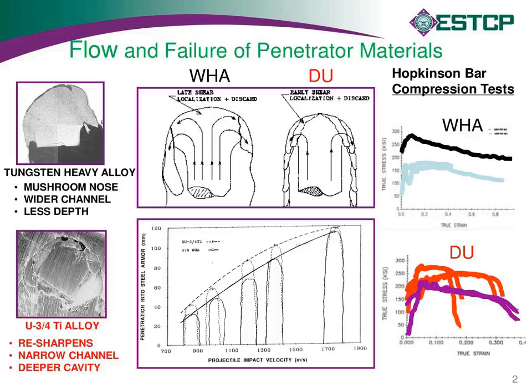The other thing I'll point out on this chart is an instrumented mechanical test where you can see this behavior kicking in. If you do a dynamic compression test, and these were done with split Hopkinson bars, where you're crushing short L/D 1 or 1/2 cylinders of DU alloys in the case of the red and purple curve at the bottom, or tungsten heavy alloys in the case of the curves in the upper plot, what you see there is that sudden drop in all the DU curves. That's occurring when an adiabatic shear band develops in that dynamic compression test.